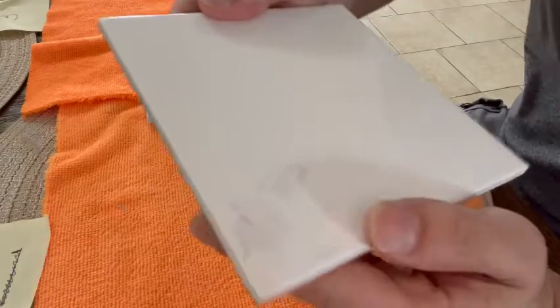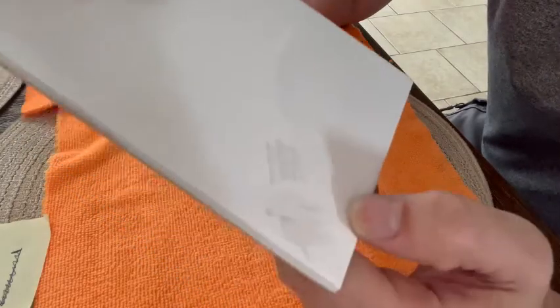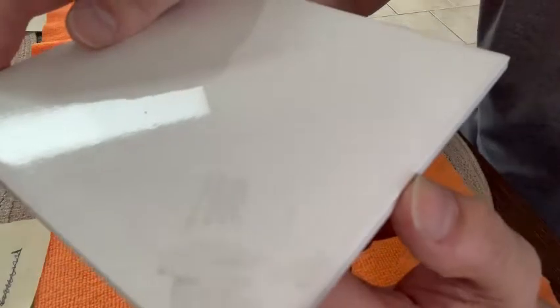If you look on here you can see it's been etched. What's interesting is the razor blade just kind of cut into the primer — it actually didn't peel it off the tile. It just cut into the primer. You can look there a little bit — the primer is actually still on the tile. So that one is: etched crosslink, Hawk Labs, Summit Coatings top coat.